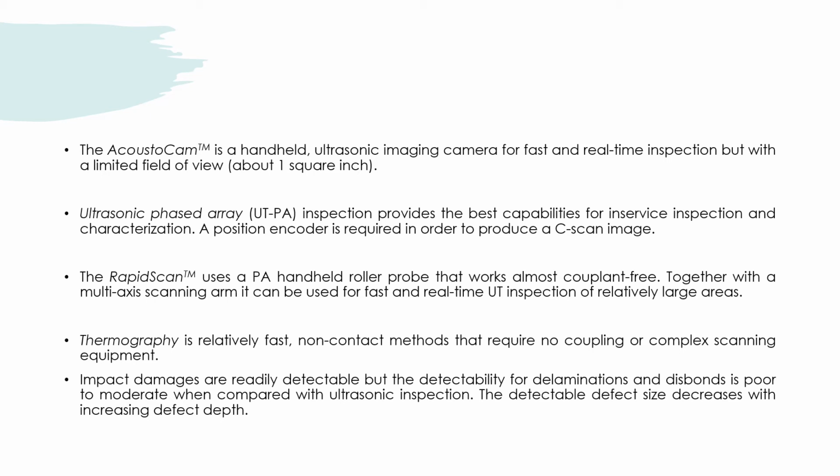Next is thermography. Thermography is a relatively fast, non-contact method that requires no couplant or complex scanning equipment. Impact damages are readily detectable, but the detectability for delaminations and disbonds is poor to moderate when compared with ultrasonic inspection.